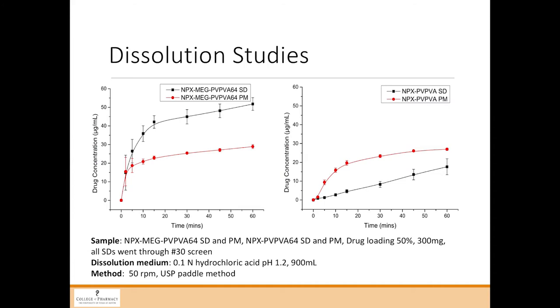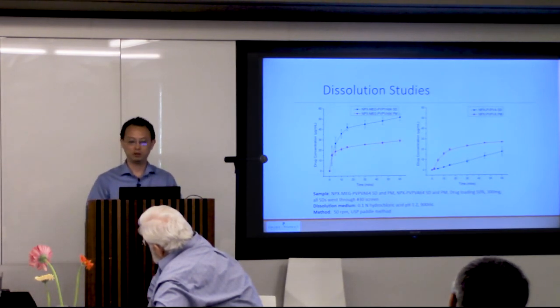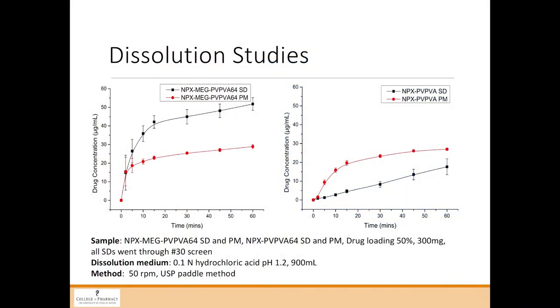So when we run the dissolution, this actually gets really interesting. This is a non-sink dissolution test. On the right, we find out that the amorphous solid dispersion actually is worse than the physical mixture. What happened is that when we had the amorphous solid dispersion in the aqueous media, naproxen crystallized so quickly, it just stayed on the surface. All the granules, actually it's worse. They don't really disperse anymore. But in the presence of meglumine, it wets very quickly, and we achieve higher solubility. Again, the solubility is not just free drug, but also nanoparticles of naproxen. So this is just another example where when two materials react, they help in the wetting and also help the formation of nanoparticles.